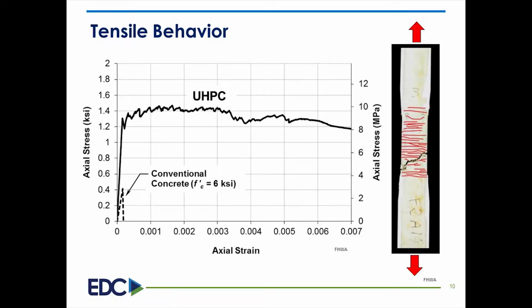This stress-strain diagram compares the tensile response of ultra-high performance concrete to that of conventional concrete. Ultra-high performance concrete is defined as having a peak tensile strength of 720 psi. In this example, the ultra-high performance concrete has a peak pre-cracked tensile strength of 1,300 psi. And the conventional concrete is showing as having a peak tensile strength of 400 psi. So the ultra-high performance concrete is about 3 times stronger in tension than conventional concrete.